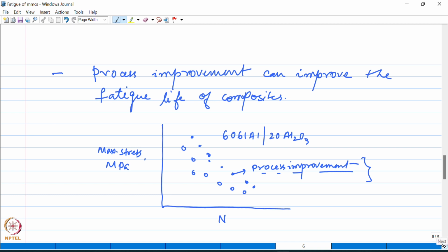Okay, and metal matrix composites are often processed by casting, and a major defect in the casting is the porosity. So in castings, the casting defects such as porosities will also have a bearing on the fatigue properties of the composites, and therefore it is also important to understand the effect of such defects, and these defects should be controlled in order to get better fatigue properties in a metal matrix composite. So these are the few aspects that one should remember while talking about metal matrix composites.